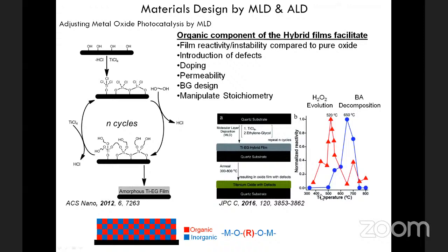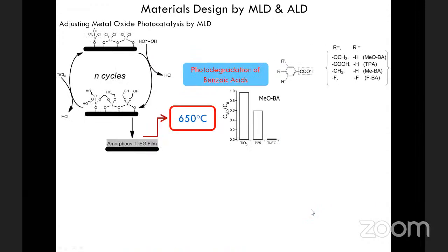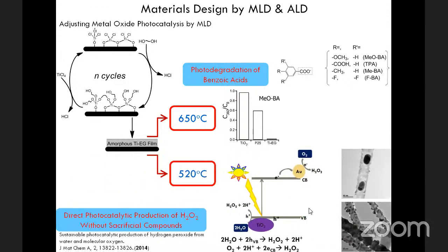One should note at this point that typically titanium dioxide cannot efficiently produce hydrogen peroxide without using sacrificial compounds, and cannot totally decompose benzoic acid because of the thermodynamics of the system. And these films can do this. So we will see what's behind it.